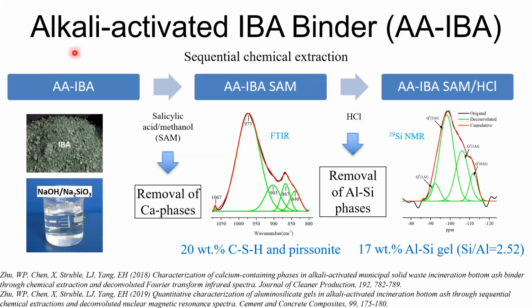Another attempt, we try to develop a high-strength binder using an alkaline activation method. As the first starting point, we try to understand the chemical structure after the alkaline activation. Here is a general IBA, and after the alkaline activation, we use a sequential chemical extraction with the idea of removing the calcium phase using the salicylic acid methanol (SAM) method. Then using FTIR, we try to specify and understand clearly what calcium phase is being removed.